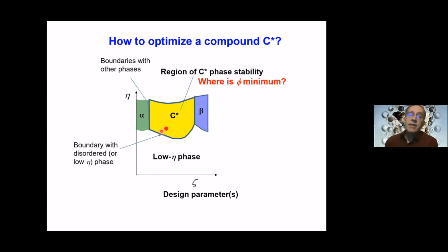But in this diagram, I'm using this parameter eta to represent a thermodynamic function that will favor order versus disorder. This eta will be either pressure or reciprocal temperature, so that for high values of that, I will favor the ordered state, and for low values of that, I will favor either the isotropic phase or some other phase with lower degree of order than the C star phase. So there will be a boundary between these two phases.